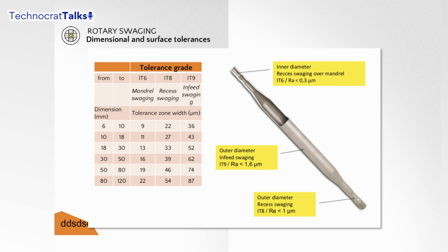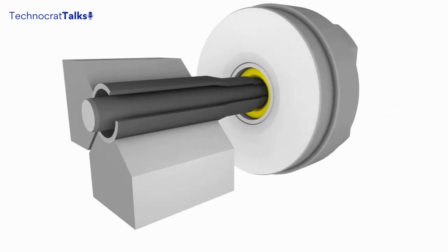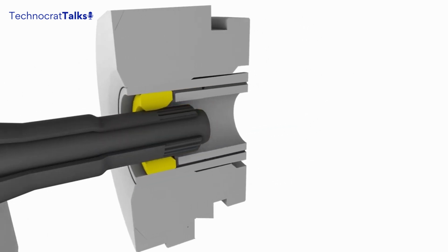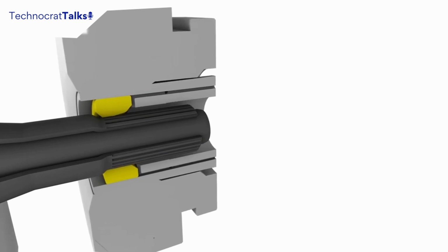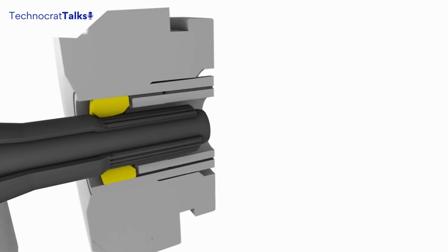Parallel to that, they started a development in axial forming, which means coaxial to the shaft or to the workpiece, and this was called axial forming. Actually, it came from a pressing idea, and we knew that each time you press a forming die over material, you need some oil in the gap in between. If you do not have that oil, your ejecting forces will increase tremendously. It's simply a friction problem.